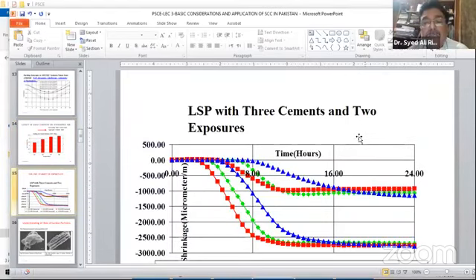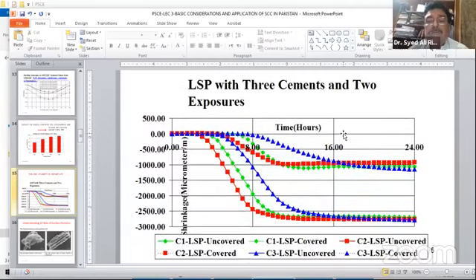Then comes the measurement of shrinkage. I have determined the measurement of shrinkage with cement and limestone powder, and this is in the covered condition, this is in the uncovered condition. So you can see with different types of cement, CEM I, CEM II, CEM III, this is the European terminology. CEM II was having 6 to 14% limestone powder, and CEM III was the blast furnace slag cement. You know, in Europe, in all the marine structures, SEM 3 is preferred because short-term strength is not the target. The actual target is very low pore sizes.